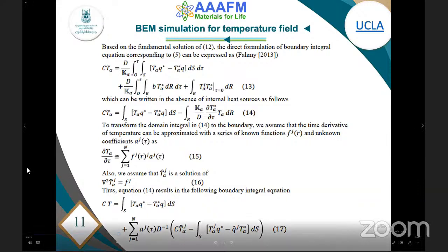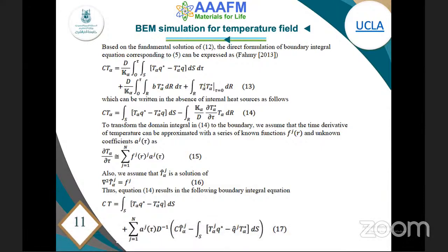Equation 13, which can be written in the absence of an internal heat source as equation 14. To transform the domain integral in 14 to the boundary, we assume that the time derivative of temperature can be approximated with a series of known functions and unknown coefficients. Equation 15 and 16. Thus, equation 14 results in the following boundary integral equation 17.